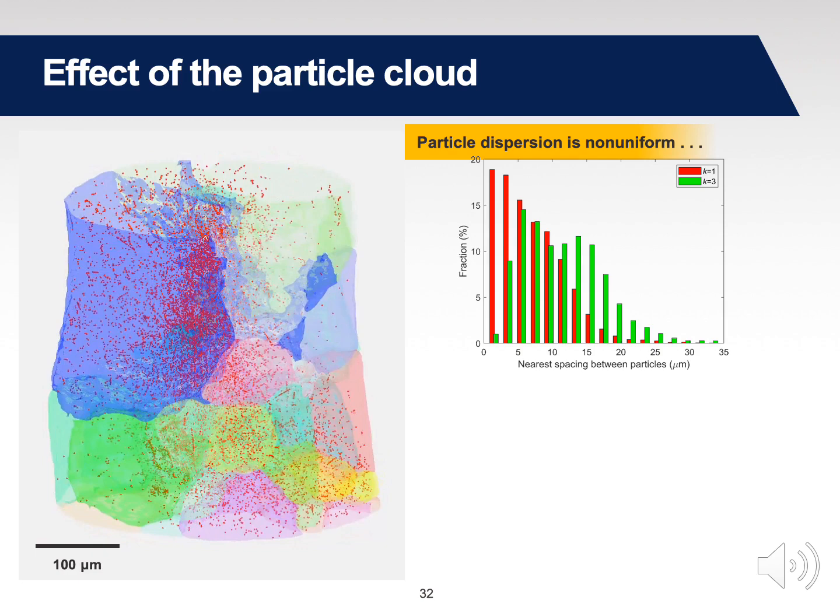You see a nearly bimodal distribution at increasingly high k value at a value of 3, which is qualitatively consistent with this observation of particle-rich regions, so regions of really low spacing, and particle-poor regions, regions of very high spacing, taken up to third order. So clearly the particle dispersion or distribution is non-uniform.